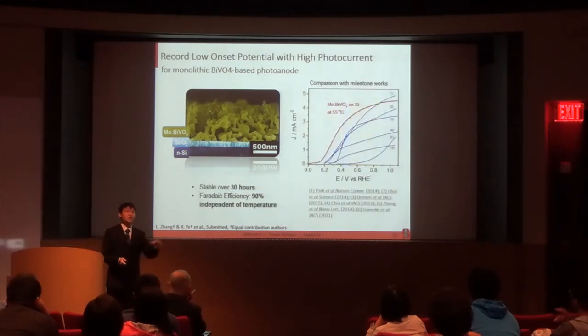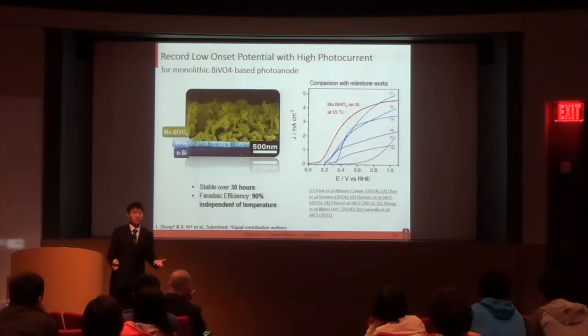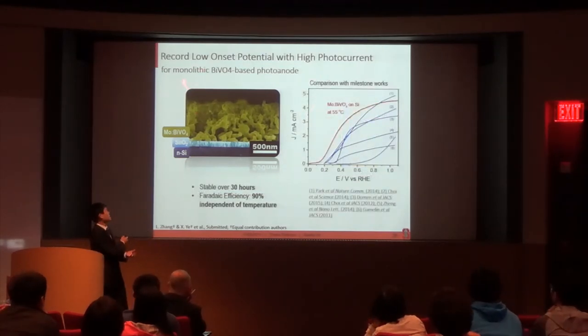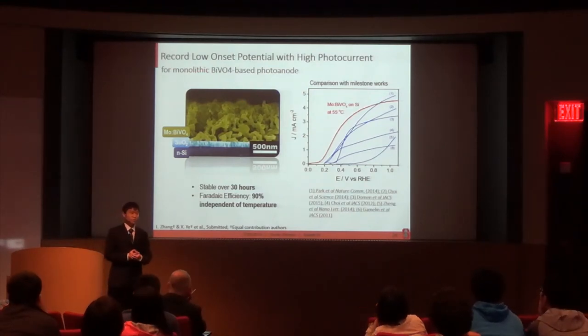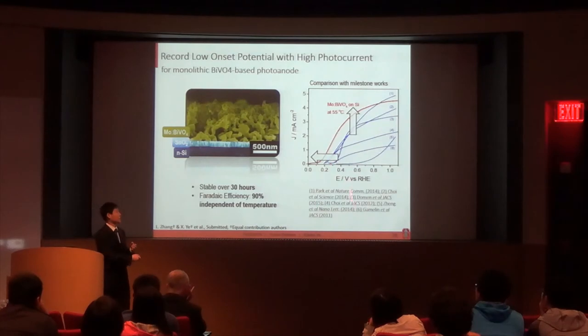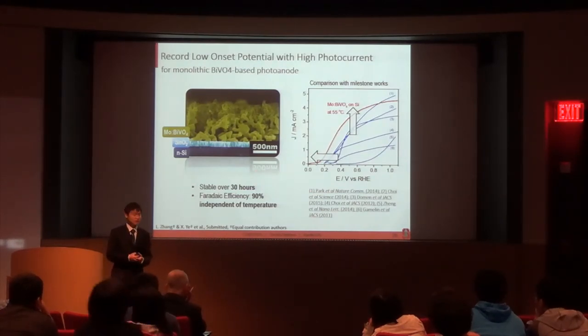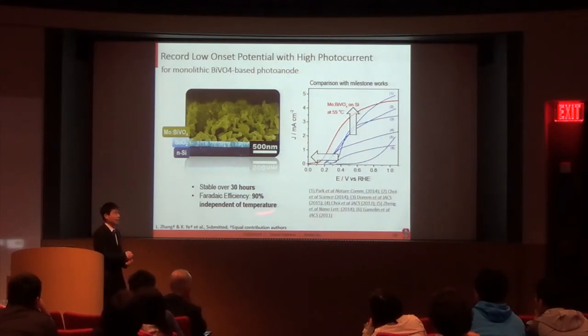And as compared to the milestone works for monolithic BVO-based photoanode in literature, we see that our device exhibits a lower onset potential and higher photocurrent at elevated temperatures. And this device is also stable over a 30 hour stability measurement, with Faraday efficiency of about 90%, which is also independent of temperature.